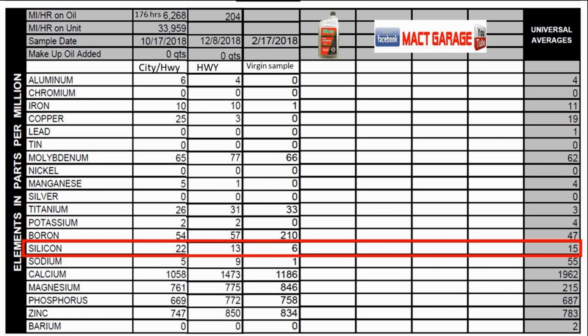Silicon, we both of course have some silicon in there. The 176-hour Ford Edge came in at 22 parts per million. My Edge with the 204 hours came in at 13 parts per million, with the virgin sample having just 6 and the universal used sampling rate of 15. So that tells us that there is some silicon from seals, and I'm going to say his is higher, mostly because it's a lot newer engine. Those seals are still leaching out some silicon, whereas mine's got 261,000 miles on it, and it doesn't have near as much leaching going on as far as the silicon.